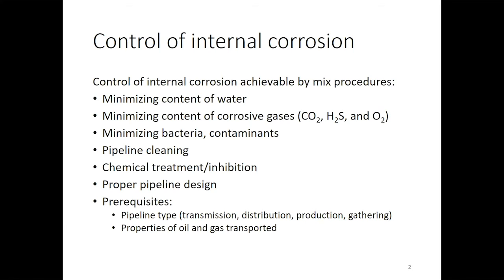So, in dealing with the control of corrosion, we keep a closer look on the content of water, of course, and also on the dissolved gases that have the ability to alter the aqueous conditions, controlling the anodic and cathodic reactions, and driving the dissolution and the evolution of the corrosion products, mainly driven by gases, carbon dioxide, H2S, and oxygen at specific locations in the pipeline. Also, bacteria and other contaminants.